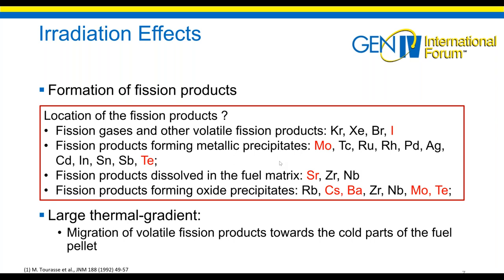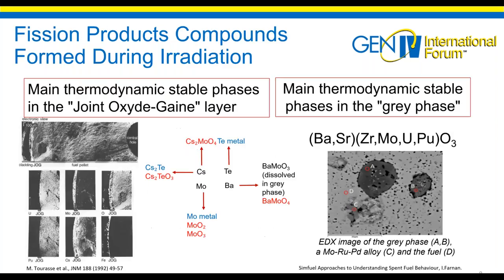So there is a very large thermal gradient between the center of the pellet, which can be like 2000 degrees C, and the outskirt of the pellet, which is generally around 650 degrees C, and this will induce the migration of volatile fission products towards the cold parts of the fuel pellet, and they will recondense, forming what we call the joint oxide gaine layer. So mainly formed by cesium, molybdenum, barium, tellurium, and oxygen.